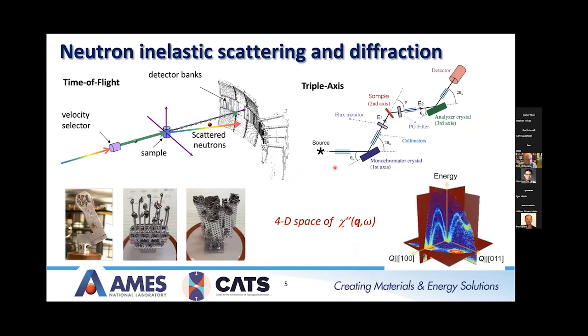All right, so the results I'm mainly going to talk about here are from inelastic neutron scattering and neutron diffraction. We have two main modes to do this. We use either a time of flight spectrometer, where you have neutrons that are created by a proton pulse hitting a target. The pulse is a bunch of neutrons centered around a certain wavelength. They're selected by a velocity selector. They go in, they hit the sample, and then they scatter into this large detector array.